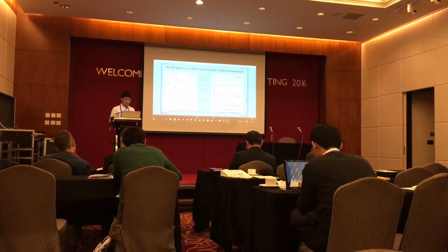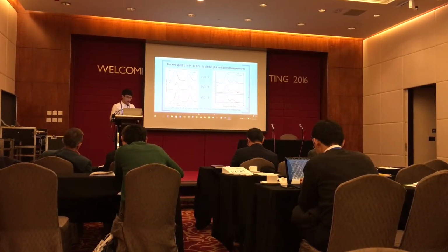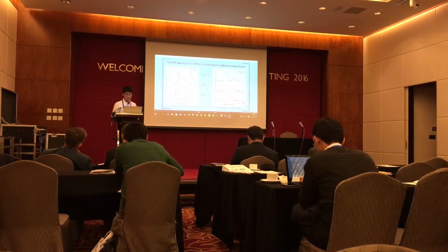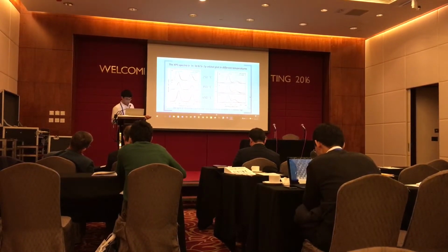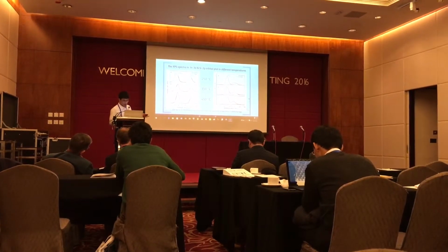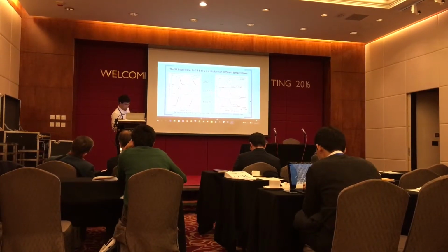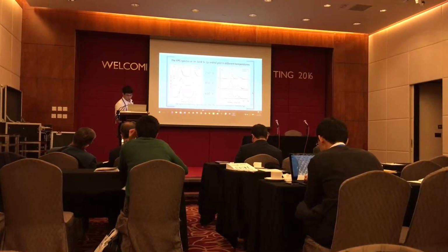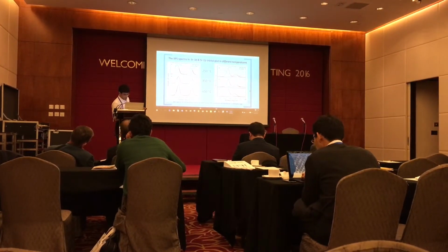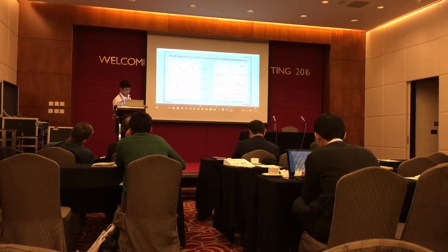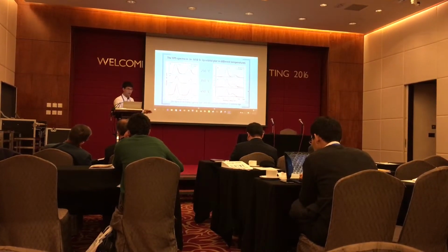Second, the probability of indium nitride disruption is higher at high substrate temperature than at lower substrate temperature. The proportion of nanodot coverage is decreased with higher substrate temperature, so the relatively stronger silicon nitride signal will appear at higher substrate temperature.